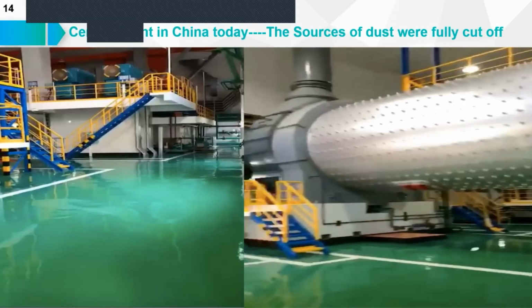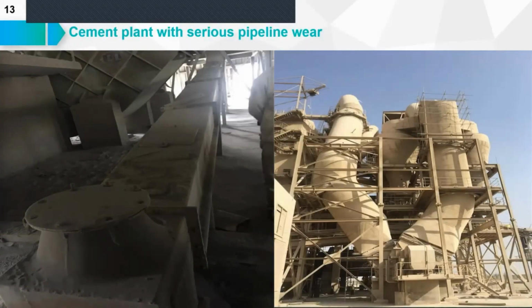So the first picture, okay, let's go back to the first picture. Here you can see why there is dust everywhere, and what causes this. Generally, from the maintenance side, it is because the metal steel pipe gets very abraded by the high-speed airflow of materials during working conditions. If the metal or steel pipe doesn't have any protection, it is going to break. Small holes often appear, especially in the elbow area, which easily wears out after a couple of months.